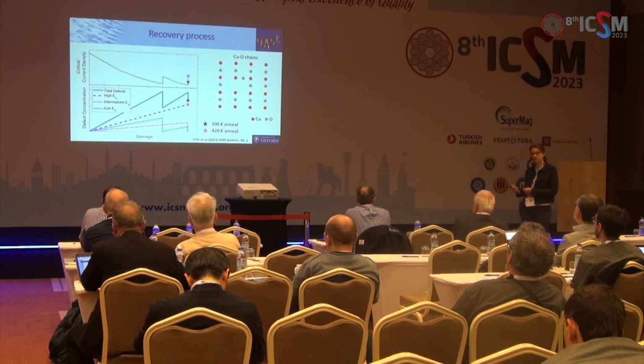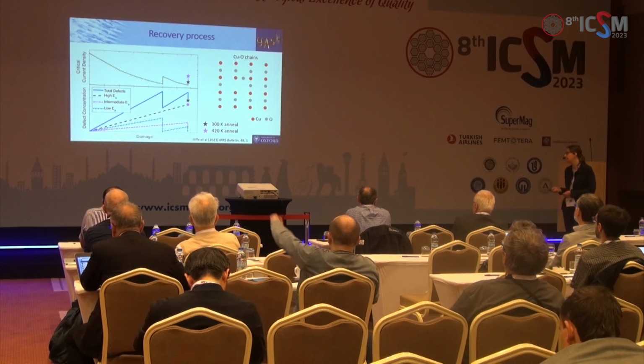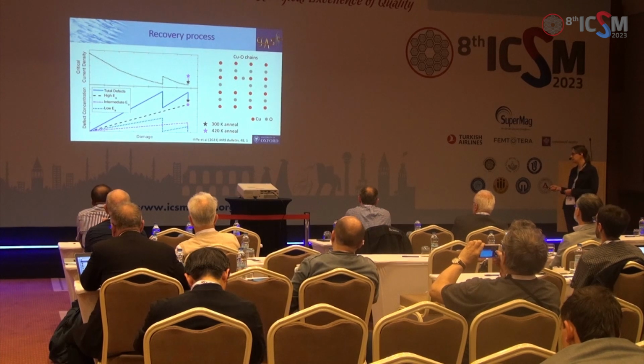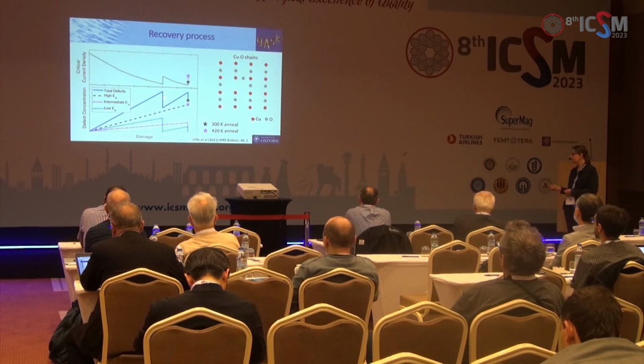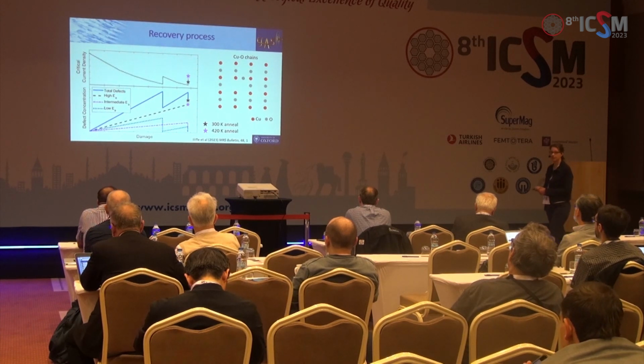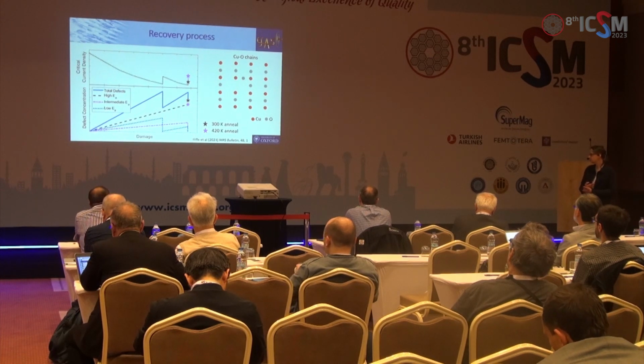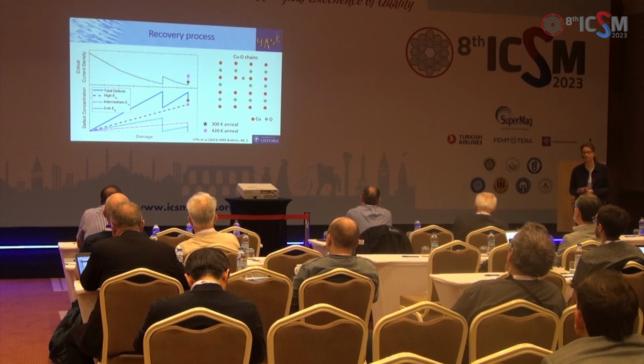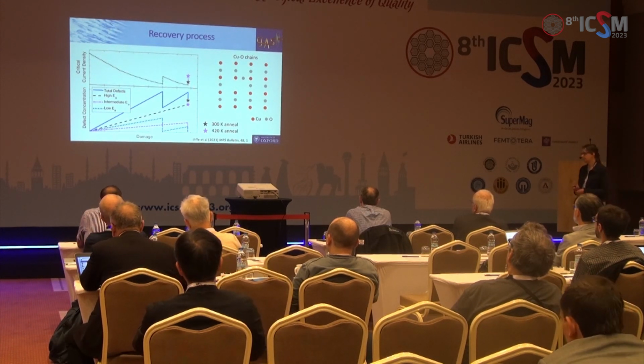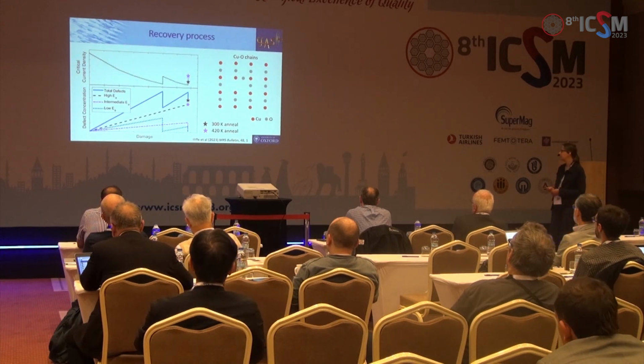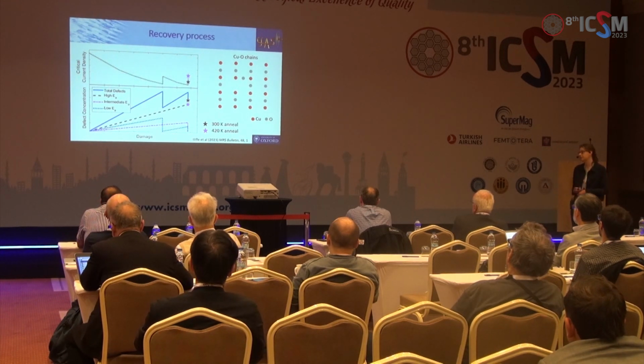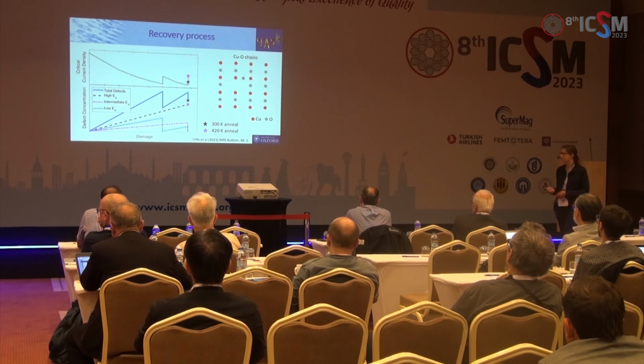Some of them have low activation energies for migration and annealing, and others have much higher activation energies. So when we go to room temperature here, we can reduce our defect population, but it's only the low activation energy defects that can recombine and anneal out. So we reduce it, but we don't go back to zero, because we have other defects that can't be annealed out at room temperature. If we go to the end here and we do a higher temperature anneal, 420K anneal, we can recover a few more of the defects. It gets better again. Okay.